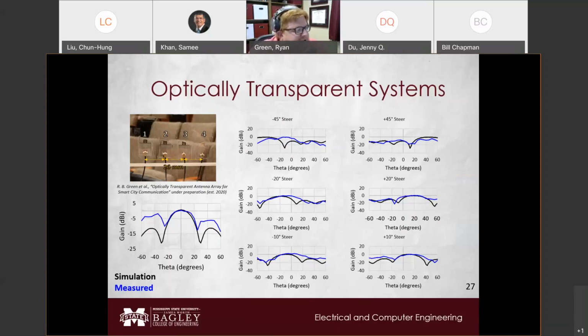And what we found is that, yeah, we can actually beam steer with a transparent antenna, much like with a traditional opaque antenna, just with the small number of antennas that we had, maybe getting up to 45 degrees on either side of bore sight. Not so possible, but with more elements, you could actually do it.